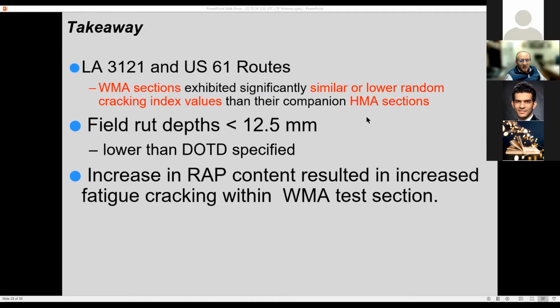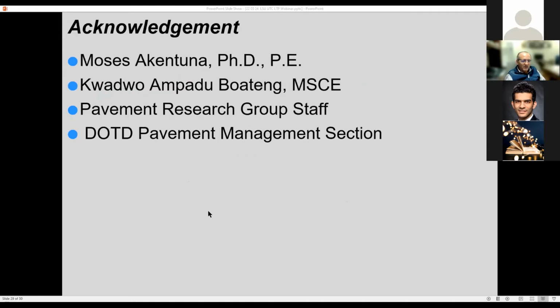And more importantly, all of them right now are below the rut depth of 12.5 field rutting that triggers an action. This is the value that tells DOTD it's time to do a rehabilitation. So far, up to 8 to 10 years, and we expect to see a whole lot more, they are all doing fine. And also, increased RAP content resulted in increased fatigue cracking for those sites that we have measured.